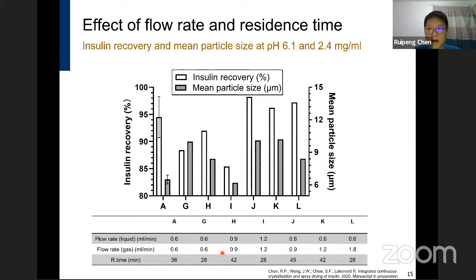And for the mean particle size, the range is 6 to 10 micrometers, which is very close to the desired size range. And of course, the measured mean particle size cannot be directly translated to the aerodynamic size range, but we think this is very close to the size that we want. So then we decided to proceed to the integrated process.